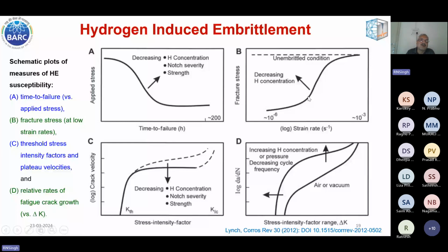Here, log of crack velocity with the stress intensity factor is shown. Though the threshold stress is not affected, in the plateau region the crack growth rate increases with increase in hydrogen concentration. And here is the stress intensity factor range. Here the threshold is affected. In air, the curve is like this. In hydrogen, the curve moves toward the left, meaning crack growth rate has increased, and the threshold stress intensity factor range has also been reduced.